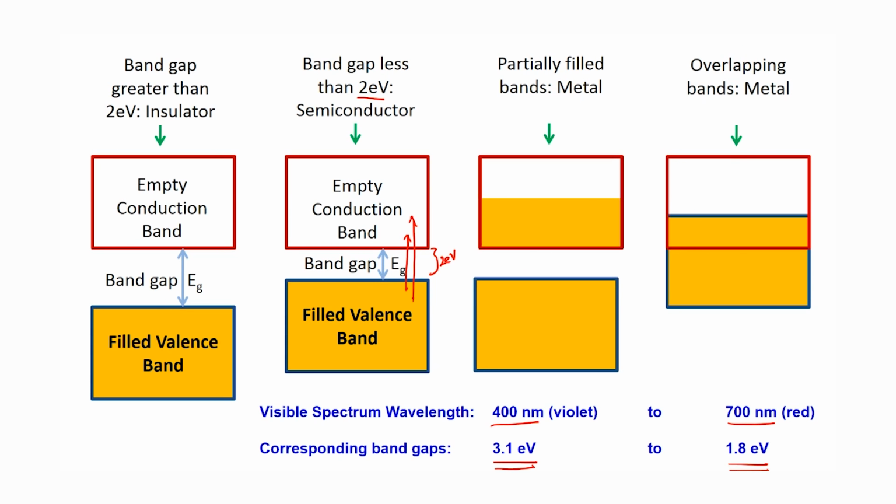But it will take an electron into the conduction band. On the other hand, the 1.8 electron volt photon that arrives at this material is unable to provide enough energy to clear this gap, and therefore the 1.8 electron volt photon is unable to do the transition. So, then what happens to the 1.8 electron volt radiation? In fact, these materials end up being transparent to that radiation.